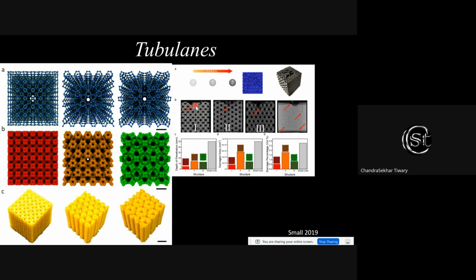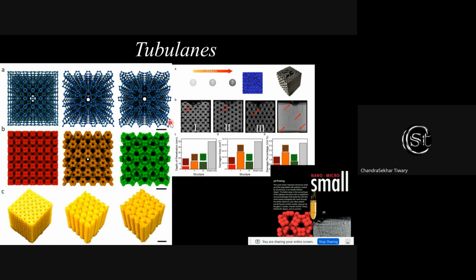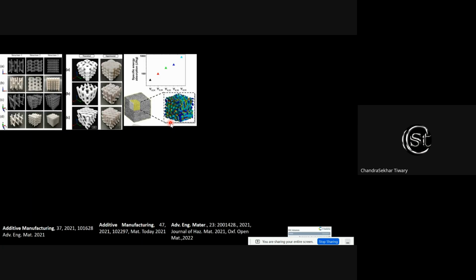But if you print them into complex geometry, you can see here we exposed it to a bullet of speed 5.8 kilometer per second, and you can see a solid metal block. If you impact it, generally you see a lot of cracks around it. Although the bullet stops, you have a lot of strain at the bottom. So the interaction or the strain transfer comes all the way to the bottom. Whereas in the 3D printed structure, you see the interconnects absorb the energy, absorb the strain, and the rest of the structure remains intact. Now, such interesting things we keep on expanding, and we have built several structures.